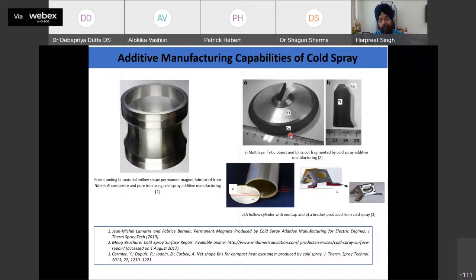For example, when I mix two powders in laser, there is always a problem, because say we have aluminum and silicon carbide, right? Both have different melting points. So they will cause some kind of problems to you. But here, since we are propelling everything and getting things stuck on the surface, it is relatively easier in cold spray. So this is another product which has been made by cold spray.